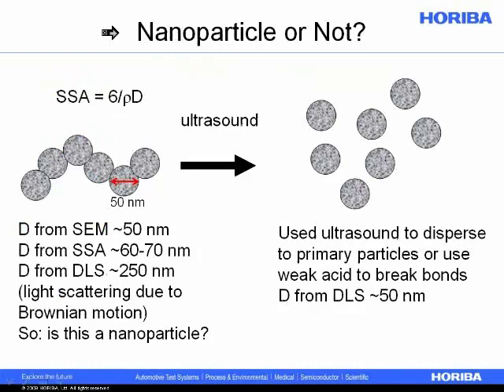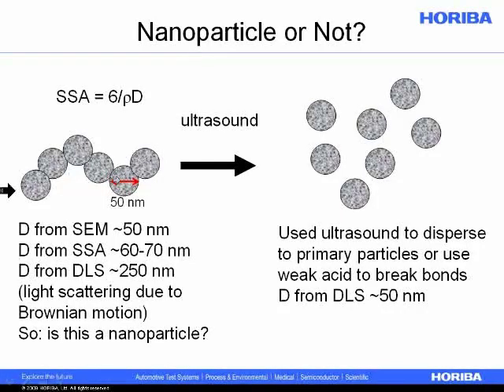This might lead people who make cosmetics to wonder: do I have nanoparticles in my products? In the world of particle size analysis, how you do the measurement greatly influences the reported size. For example, if we're creating nanoparticles where each particle has a diameter near 50 nanometers, and I measured this using a scanning electron microscope and just measured the diameter, I would report this as a 50-nanometer particle.